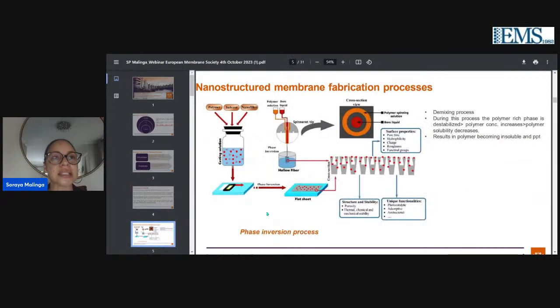We have looked at different types of fabrication, the phase inversion process, where we basically have your polymer and nanofiller, and your solvent. This is combined together to form a casting solution, which can be cast on your membrane. And via phase inversion, you could get your flat sheet membrane.